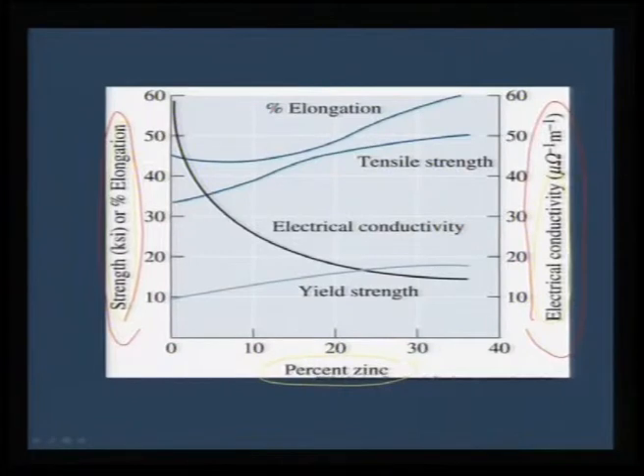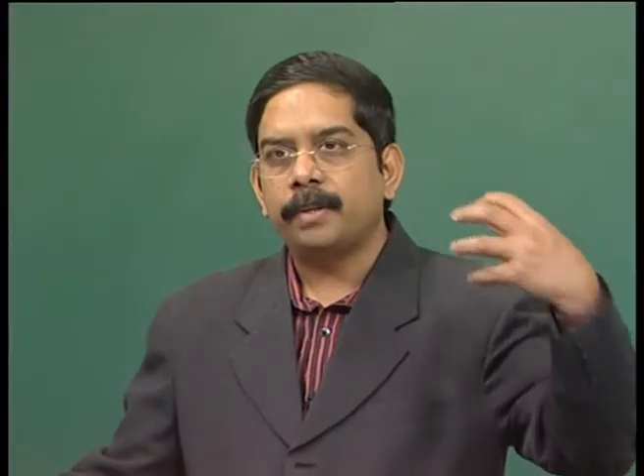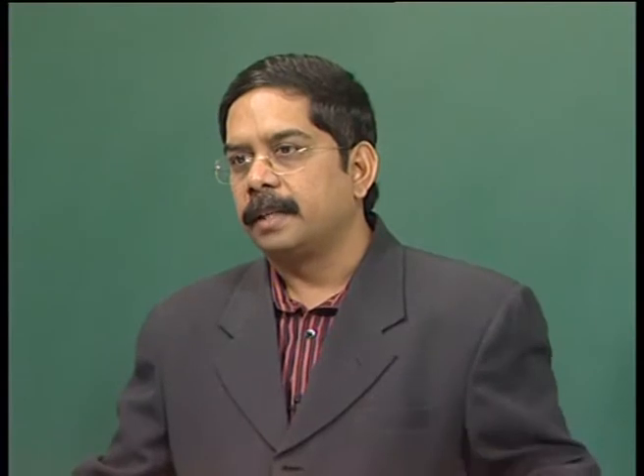So, if you take this view graph where percentage zinc is plotted against the physical properties, one would see that the elongation curve is increasing with increasing zinc percentage, so is the tensile strength, so is the yield strength. Whereas, if you look at the electrical conductivity for the solid solution, it is exponentially decreasing. So, the solid solution does not necessarily have to aid all the physical properties, it can influence one while losing on the other, but we need to understand